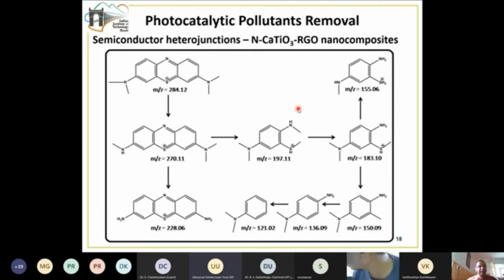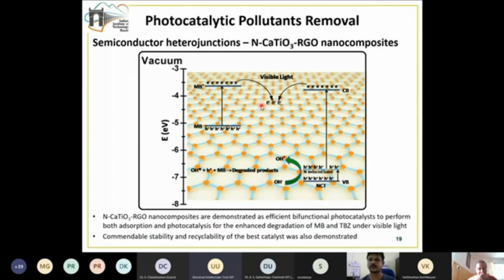But what are these byproducts which are being formed, and are these products toxic or non-toxic? We haven't done the toxicity analysis, but at least we could decipher what byproducts are formed by doing a detailed degradation pathway study using the HRMS technique, or this LC-HRMS technique. We could take this MB dye, and it gets broken down into these much smaller fragments formed from the MB dye during the photocatalytic degradation. Then based on all these results, we were able to decipher a mechanism for this entire process.